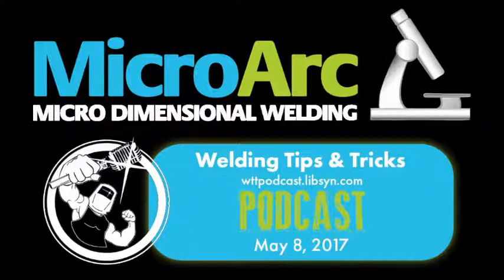That's an important point. Right, and certain machines have a capacitor discharge arc start in lieu of a high frequency arc start. It's a whole different way the arc starts, and a lot of times I'll just scratch start, because I can't deal with the high frequency wandering around on fine details. You start melting little corners, and even a tiny little melted corner on a mold component is a big deal, because you're not going to go in with a file and take it off. It has to be precision machined off, and then either EDM'd or milled or ground off precisely. You might be involving some type of mold texture, and now all the texture's screwed up.